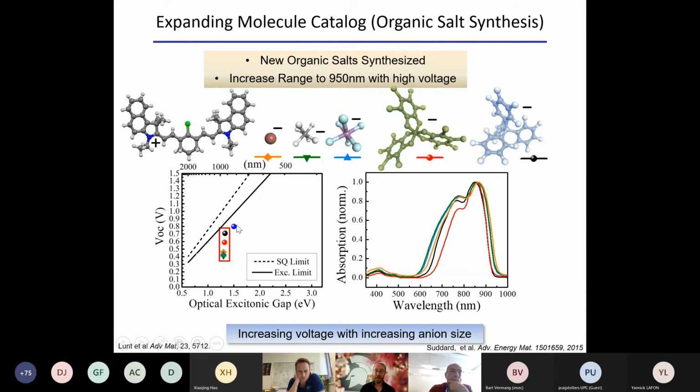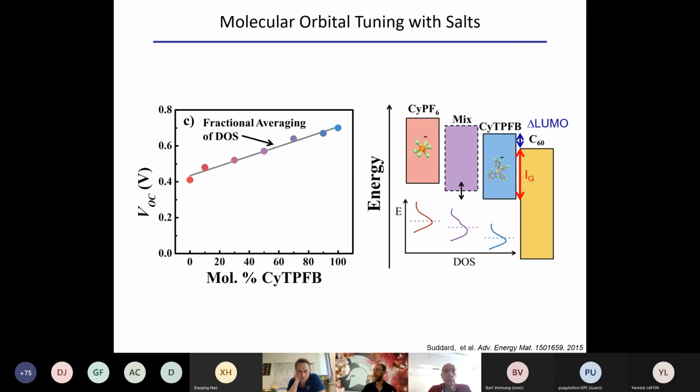We liked that particular thiocyanine because it gave us such a high voltage. And so we didn't have to go and design thousands of molecules stabbing blindly in the dark to get the right voltage. We were able to just optimize the voltage. And it took us a while to figure this out, but it really came back to the counterion actually acts as a dipole induction layer that can affect at the molecular scale the HOMO level.